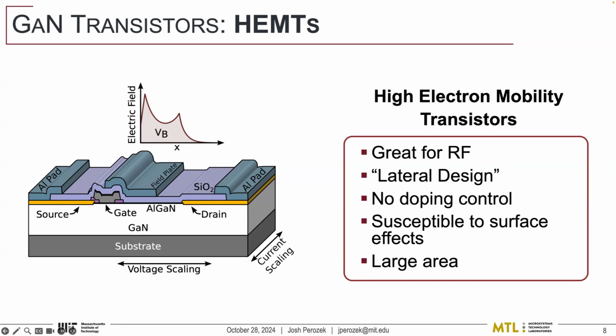That's great. It gives you very high mobility. It's bad in that you can't control how much charge is there. So we're never operating at the optimal trade-off point between dopants and distance that lets you really maximize the breakdown voltage for a device. We get around this by playing tricks like having field plates and things, but as you can see from the electric field up there, it's not uniform, it's peaky. That adds problems to your reliability.